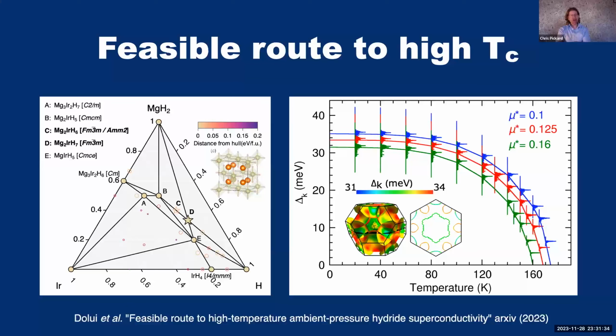So there's a very closely related Mg2IrH7 cubic phase that, if we could encourage it to lose a single hydrogen, it would become metallic, and we predict a high temperature superconductor, which, according to our calculations, at ambient pressures has a Tc in excess of 160 Kelvin.